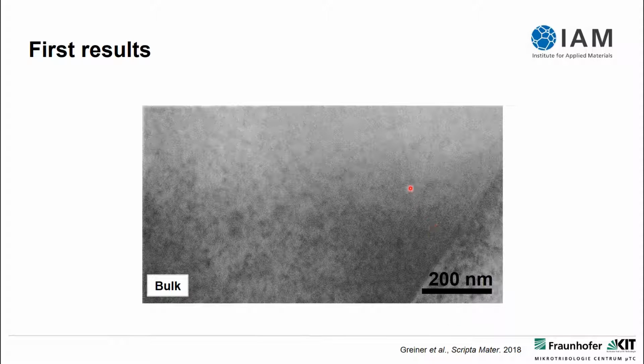So what you see here is a cross section. We are looking from the side into the wear track, basically. Here's the surface, and this is where the sliding is happening. Our sample preparation method is such that we electropolish our copper samples after annealing, grinding and polishing them—there are electropolishing steps—so we have a very low defect density structure to begin with.